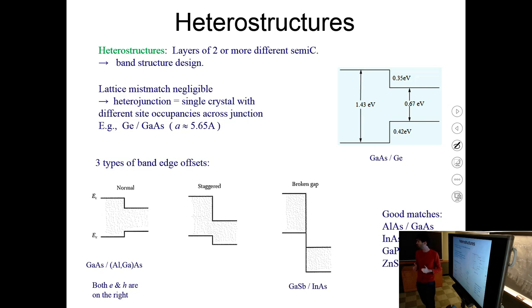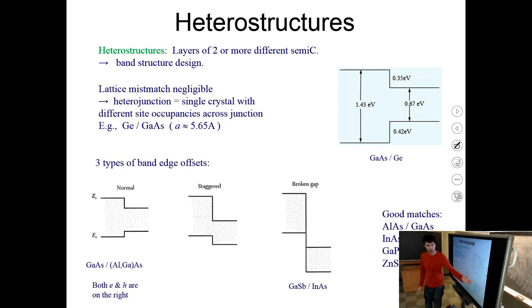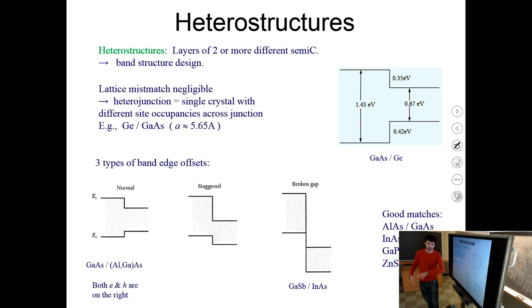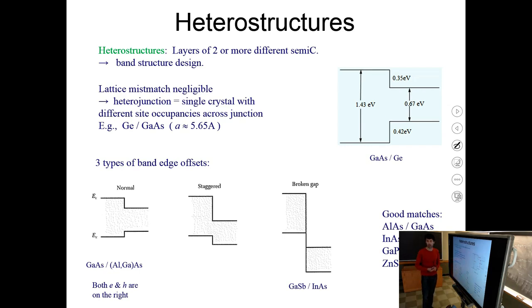There are several examples of well-matched semiconductor pairs: aluminum arsenide and gallium arsenide is a very common combination used in all kinds of devices. Indium arsenide and gallium antimonide are used in infrared applications and in the new field of topological science. Gallium phosphide and silicon are almost perfectly matched, and zinc selenide is matched to gallium arsenide.